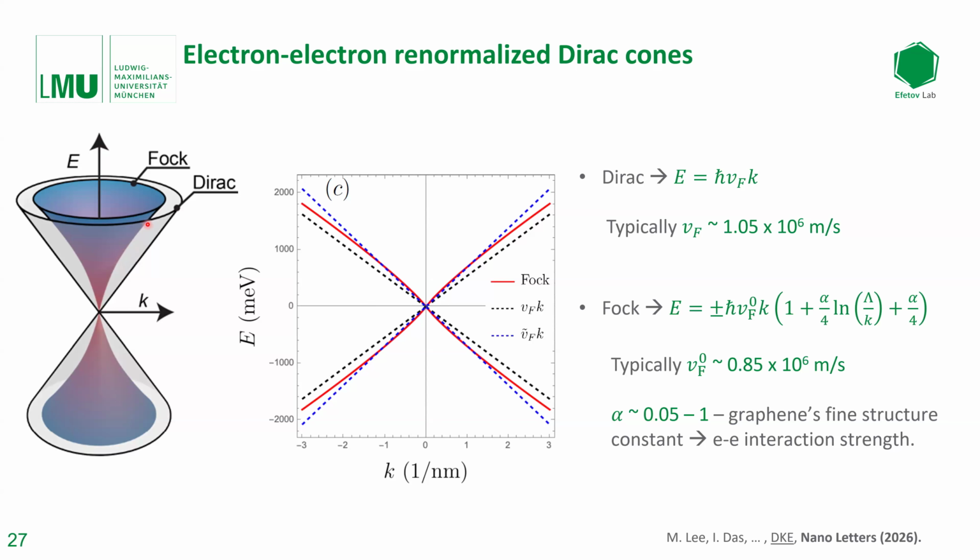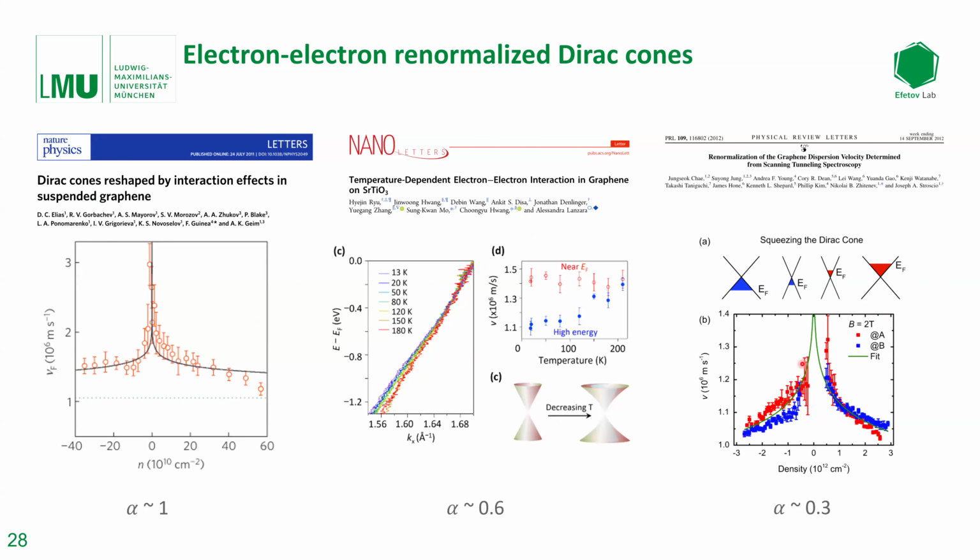However, when you start filling up the Fermi energy in the band structure, more and more electrons get populated. They much more efficiently start screening one another, and therefore the Fermi velocity drops substantially. And this sort of transition basically gives something which these theorists have shown has a logarithmic correction to it. And this basically results in a slightly nonlinear band structure for the graphene.